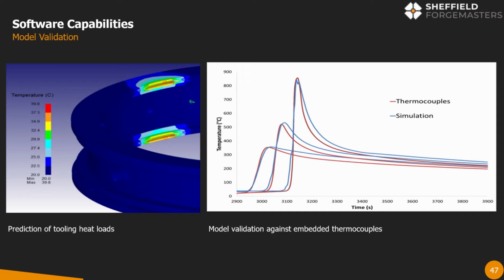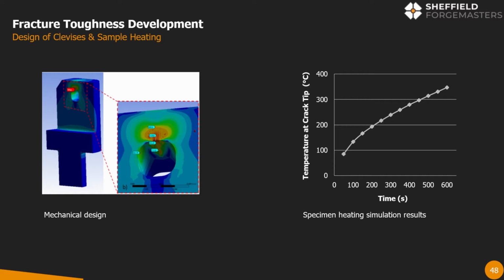Okay, we're also developing fracture toughness testing work on this. Some of the materials that we've proposed, so I've showed some of the high strength and high toughness requirements and properties that we get out of these materials. So they also give the test rigs that have to test them a lot of grief as well. So we're having to redesign a lot of the handling clevises around that and developing the high and low temperature test capability. So we have to be able to heat these samples to test the appropriate ranges for where the materials will have to operate and quantify their toughnesses over that temperature range.